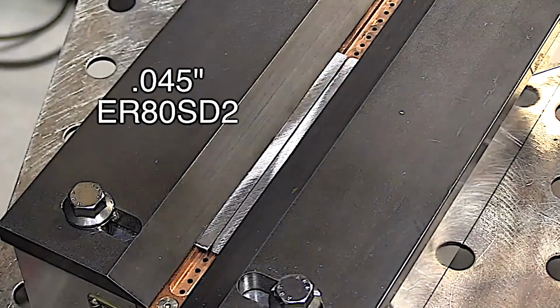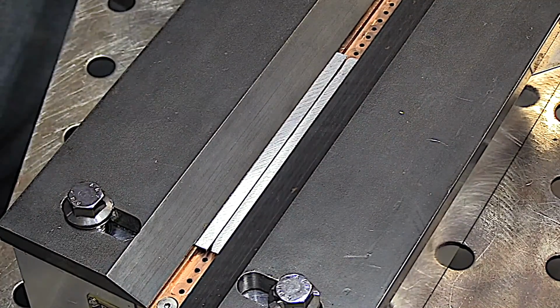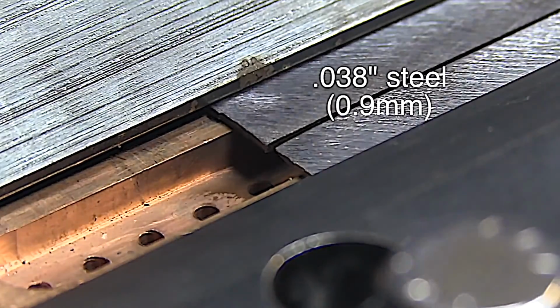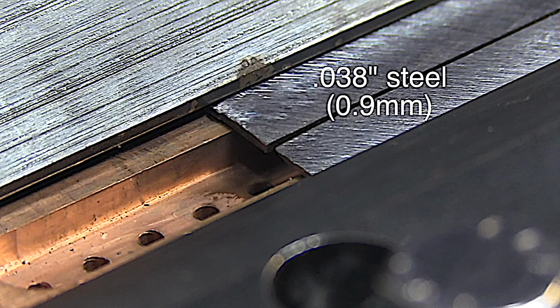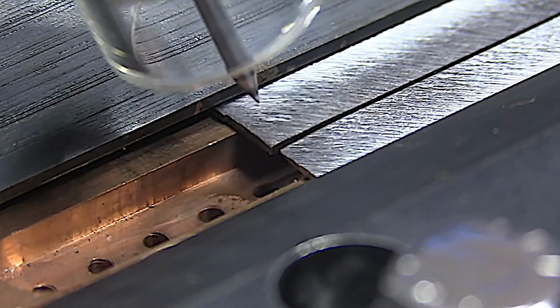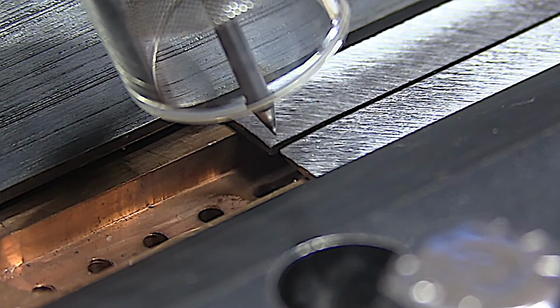I'm using a .045 ER80 SD2 filler because the thickness of the base metal is less than .040. You can see that I have just a little whisper of a gap there. The gap is totally not necessary. You're going to get penetration pretty much, but the gap helps a little bit in distortion. So I got a nice low startup. This machine has a 5 amp startup, very helpful for aerospace type work like this.